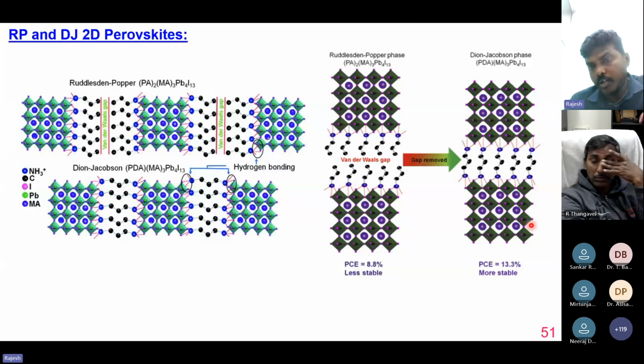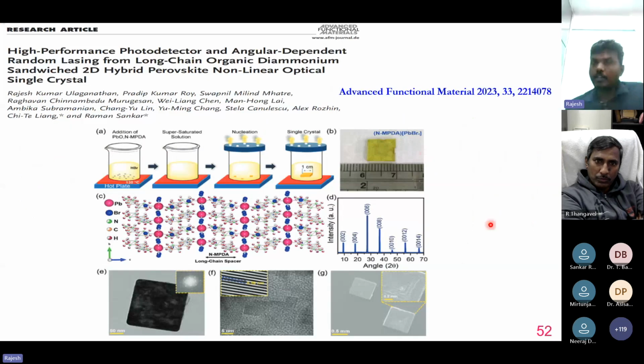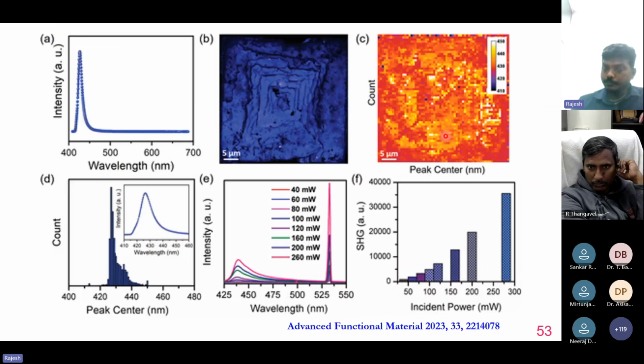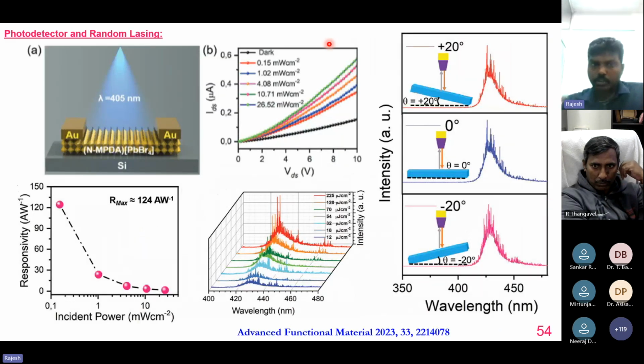In this paper they have reported that in the presence of the van der Waals gap, the efficiency is around 9%, while removing the van der Waals gap, they are able to increase the efficiency to almost 14%. In this study, again by solution growth, we grew bromine-based 2D materials using a different spacer and achieved good stability all over. You can clearly see the photoluminescence mapping shows that our grown perovskite has photoluminescence everywhere. Then again, we showed photodetector performance, and we achieved a very high responsivity.